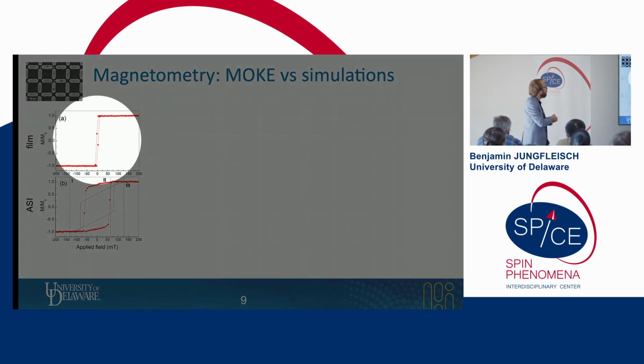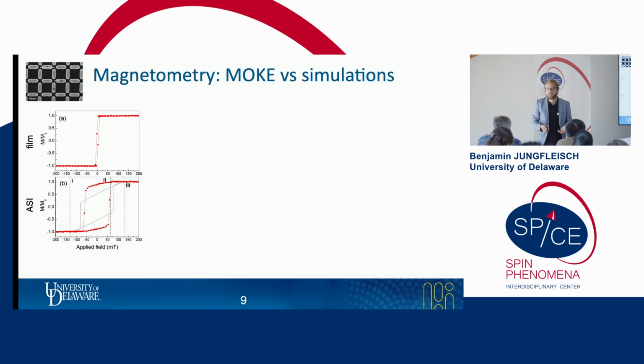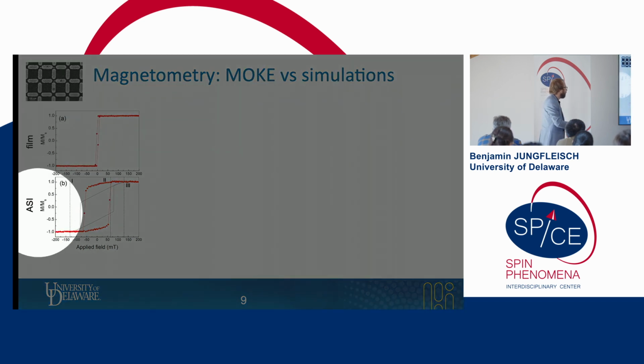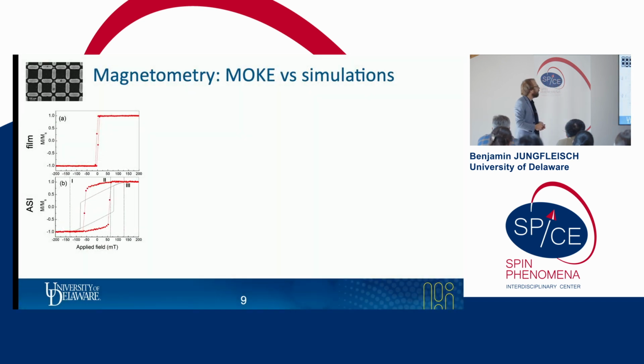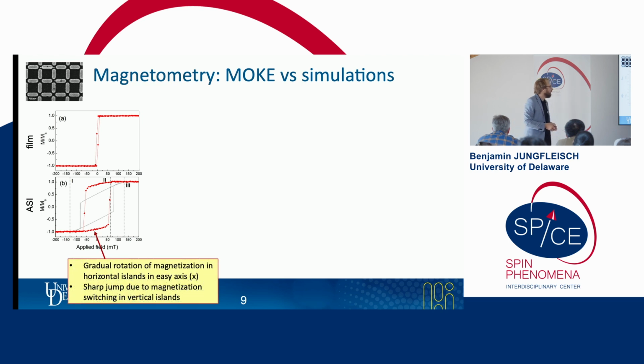On the top, we see the film. We essentially see a step-like function. There's almost no coercivity. This is what we would expect from the film. And at the bottom, we see the artificial spin-ice network with three different regions. Region 1 and region 3 are the saturated states. And in region 2, we see a gradual rotation of the magnetization in the horizontal elements. Imagine first we saturate the system along the y direction, so all the moments point upwards or downwards in the vertical direction. Then we lower the field magnitude, and the moments gradually rotate into their easy axis, which is along the x direction.